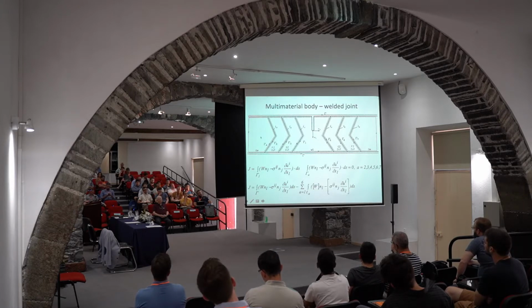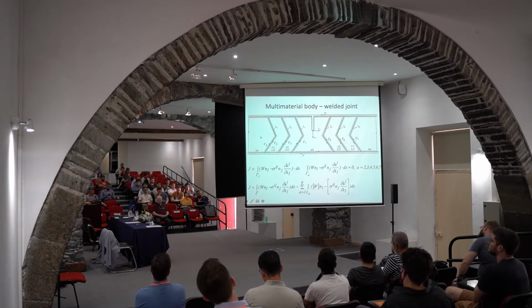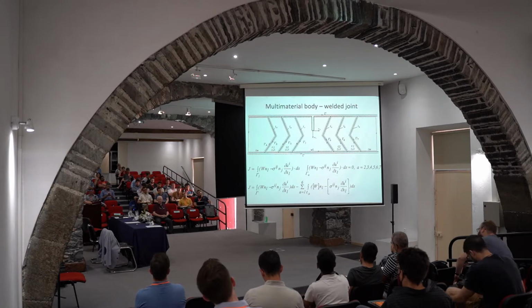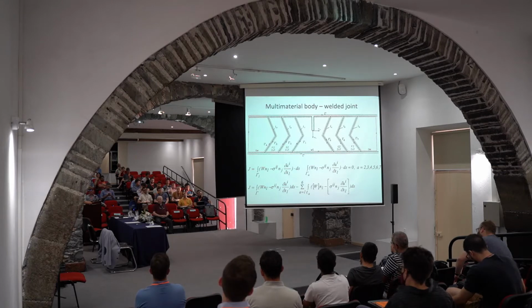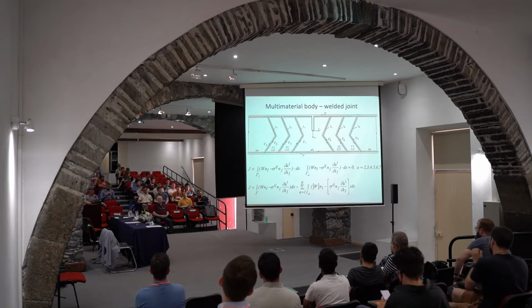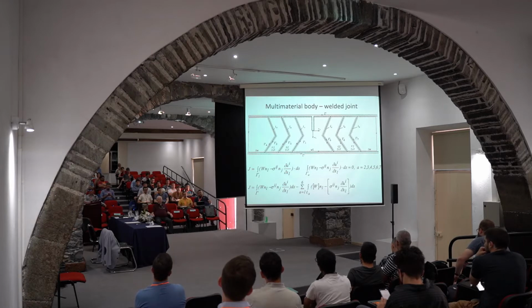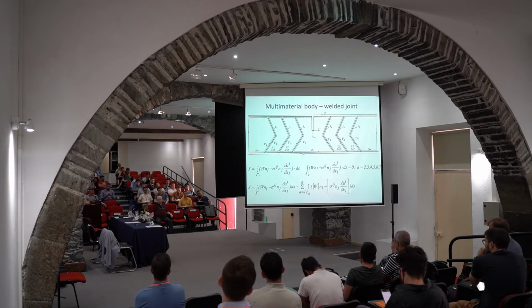At least these four regions have different properties, but with common steels, and I'm today talking about steels mostly, these differences are not a big deal. You will see later on, we pick up to about 10%, maybe 20% of difference in properties, and then maybe 10% of an error. Nevertheless, if we would have considered a welded joint of ferrite and austenite steel, then we would have a much bigger difference. Now, in our practical experience, we didn't face that problem, so you will see that my conclusion will be that although theoretically a big deal, practically this is not a big deal.